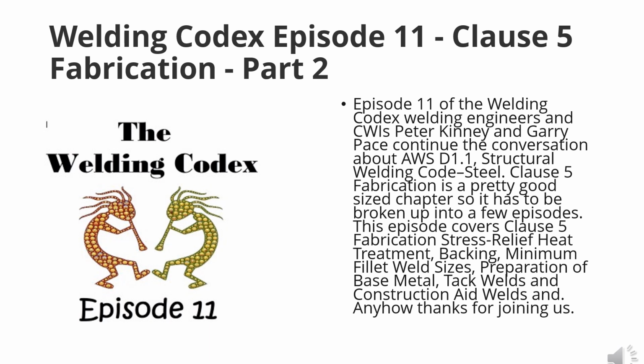Once again, before you dive into this, if you are a rookie and you get thrown to the wolves, just do some reading, take an extra hour or two, put together what you're going to do, and generally things will come out. And Pete said here, steel's not recommended for post-weld heat treat. Stress relieving of weldments of ASTM A514, 517, A709 grades HPS 100W, and ASTM A710 steels is not generally recommended.